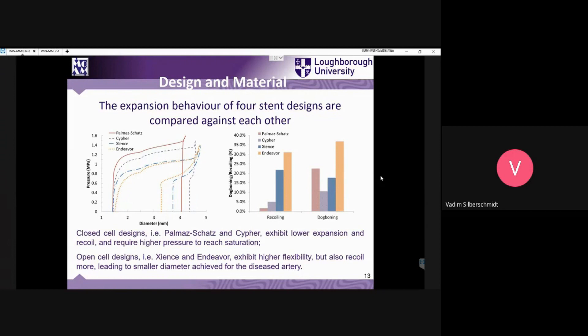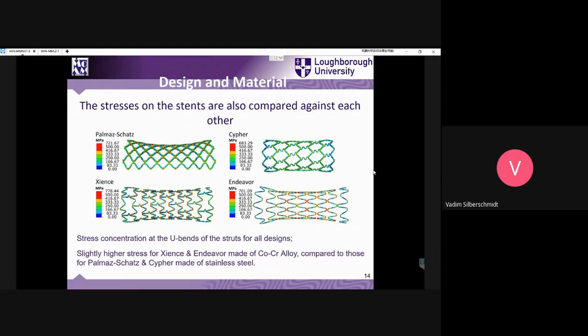The graph in this slide shows the behavior of four different stents. You can see clearly that we have a residual radial deformation. The diameter at the bottom shows the residual diameter of the stent after it has been opened. You can see the distribution of von Mises stresses — surprisingly, for such relatively tiny components, the level of stresses is very high.